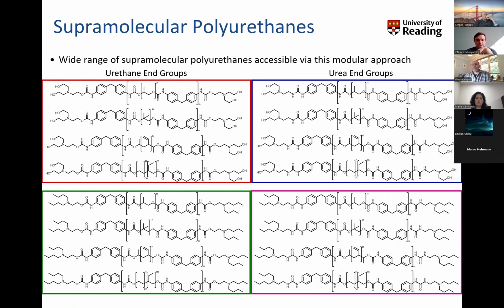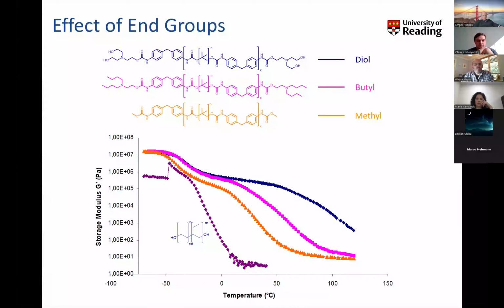Typically the way that we have studied these materials is using rheology. And the way that we've studied the rheology is typically as a temperature sweep, because that is most relevant to the use of these materials as hot melt adhesives. What the industrial sponsors were interested in were materials which had very distinct thermal transitions within very narrow temperature ranges, such that you could melt and cool and go from fluid to solid very, very quickly. And that's typically what you require from a hot melt adhesive.